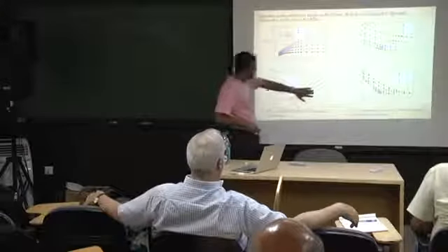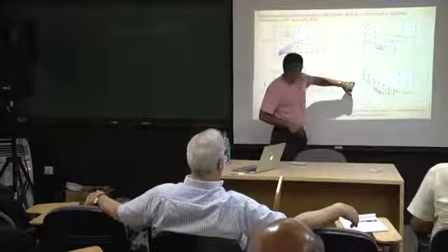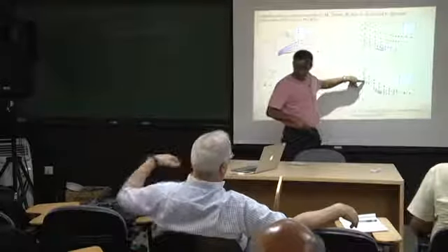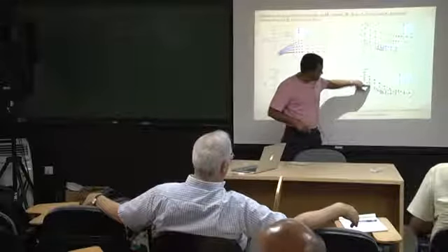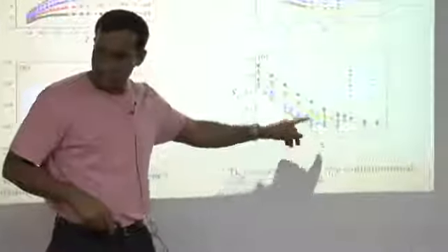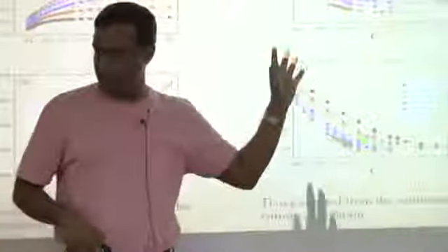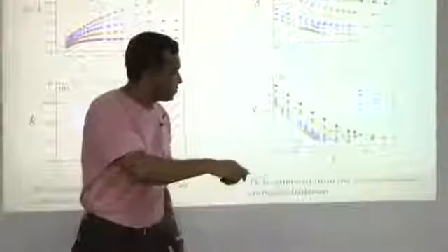So this is the figure you should look at. Here is the configurational entropy plotted as a function of pinning density for a given temperature. As you increase the pinning density, it hits zero at some pinning fraction. For a higher temperature, this hits zero at a bigger pinning density. As you go to higher and higher temperatures, the pinning required according to their calculation becomes more and more.